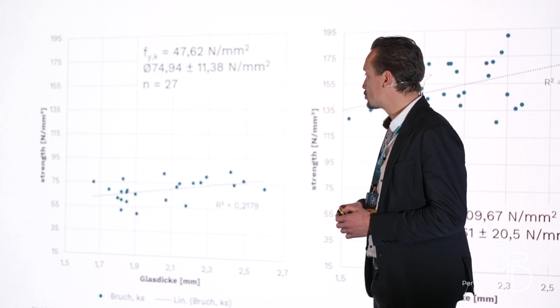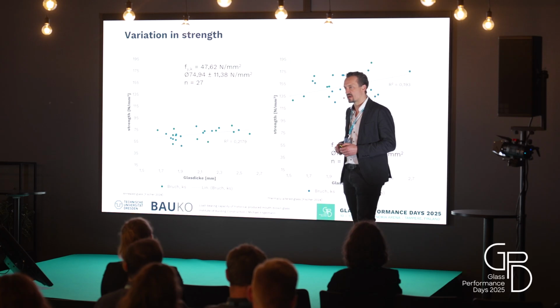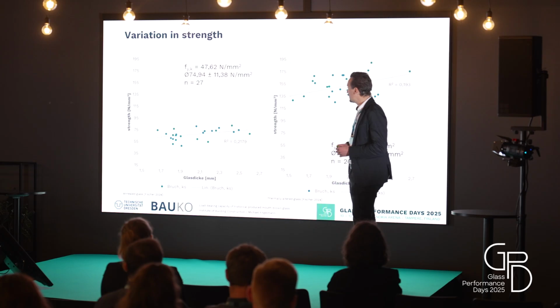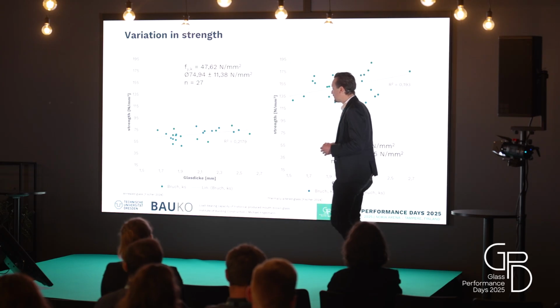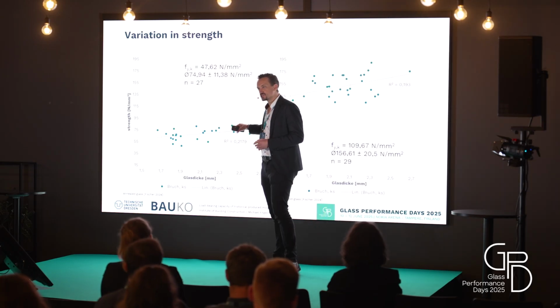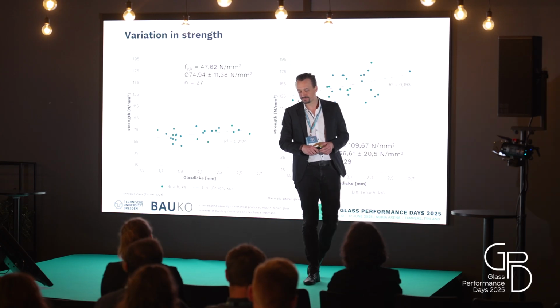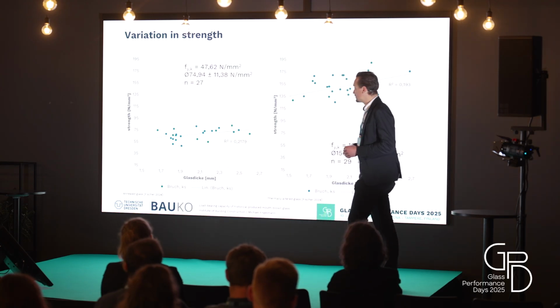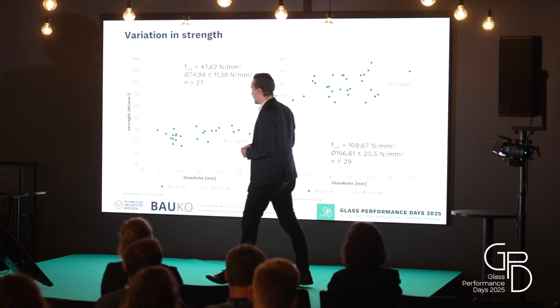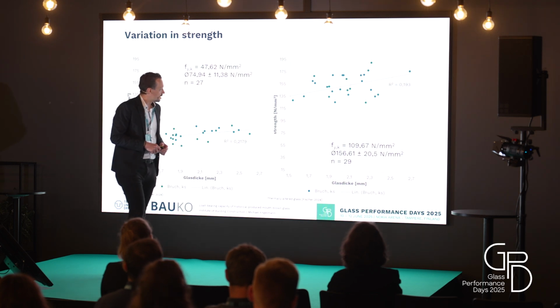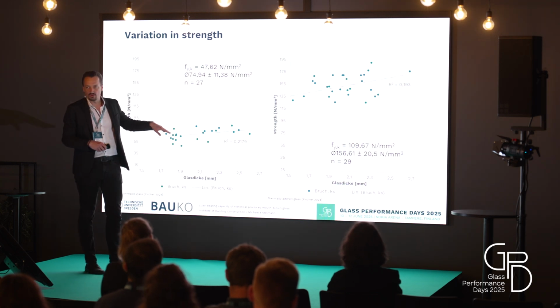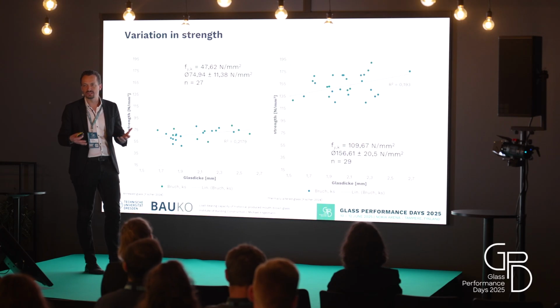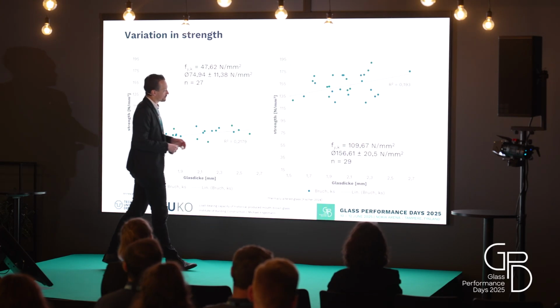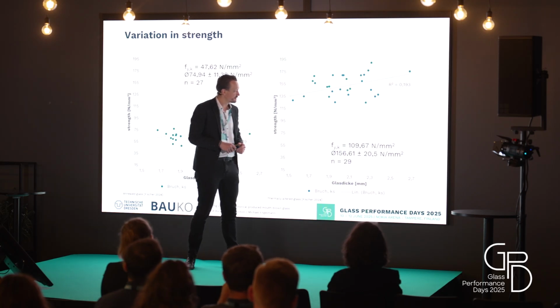So the edge treatment was really precise and turned out to be nice results, but we didn't find any significant correlation when you look at the thickness here. On the other hand, after thermal treatment, you find the values here on the right-hand side. Again, there is no correlation with thickness, so the surface compression does not reflect in the strength of those samples, and we find a characteristic value of about 110 megapascal.